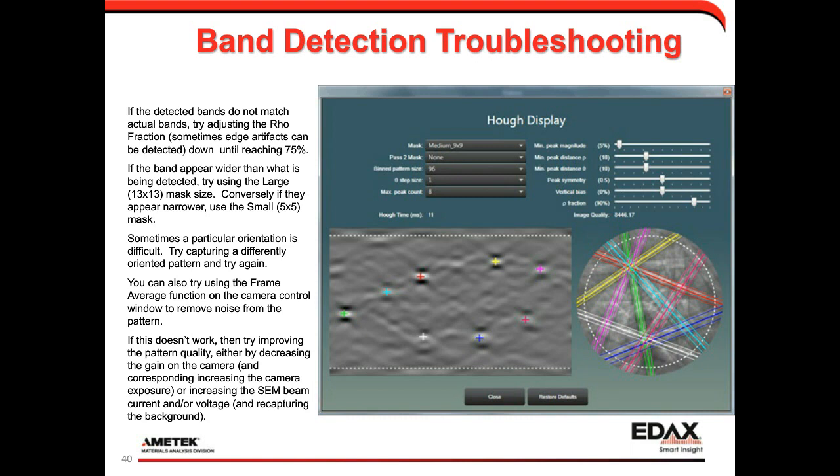So this is going to be the main settings you're dealing with. The other thing I usually do with the Hough is I deal with the vertical bias. The vertical bias is very, very sensitive. I usually take it to 1, 2, or 3. And what that will do is essentially move what the Hough space here on the left, the square area, it'll make sure that I'm getting away from the bottom, choosing more toward the top. Again, it's extremely, extremely sensitive.